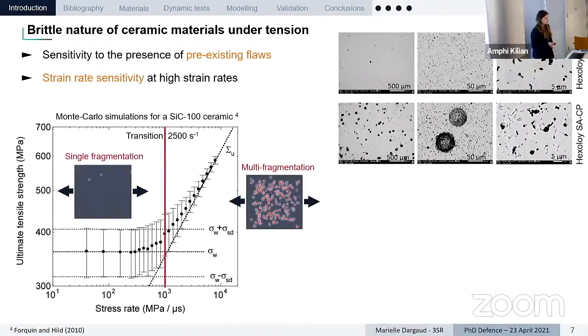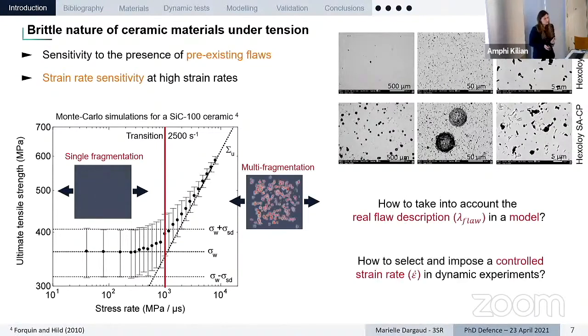This is due to the fact that according to the loading rate, we are going to induce a single fragmentation on few defects or a very intense multiple fragmentation after a certain threshold. So there are two main questions that I'm going to address in this work. The first one is how to take into account the real flaw population in a model, and then how can we select and impose a controlled strain rate in dynamic experiments?